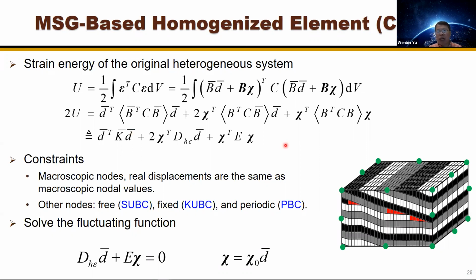And here, of course, we need to apply some constraints. Constraints first for the macroscopic nodes, these nodes here, because that's the global element. And the real displacement should be the same as what we calculated in the global structure. And then for the surface elements, these nodes not captured in the global analysis, there are several ways to apply constraints. It depends on your situation. If it's stress-free, then we should let it free if it's a free surface. If it's connected with another surface, we need to use the so-called periodic boundary condition. In such a way, we allow it to vary